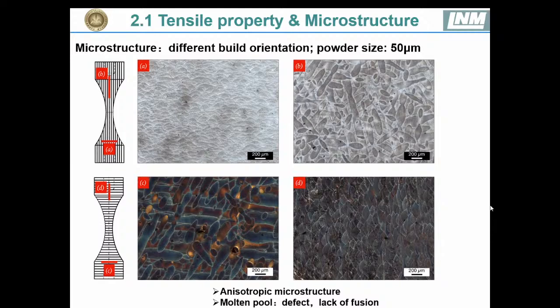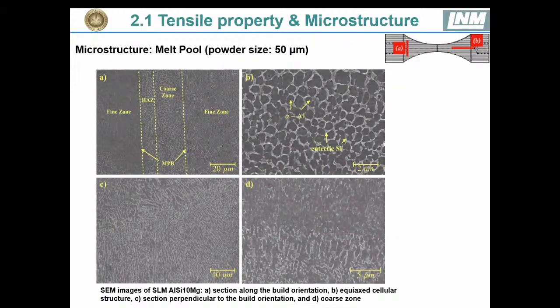And also with others, we can also see this non-uniform microstructure. And by scanning electron microscopy, we can further observe the microstructure. We can see the microstructure includes 3 different zones. And here there's a fine zone, heat affected zone, and a coarse zone. And here the microstructure is a kind of cellular microstructure.